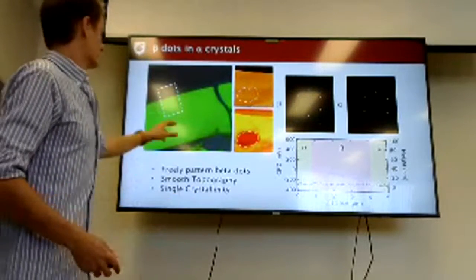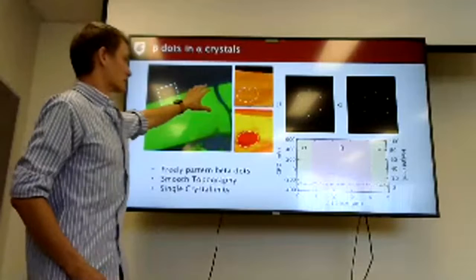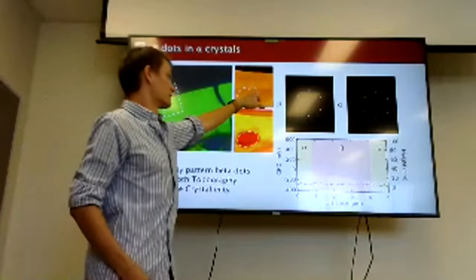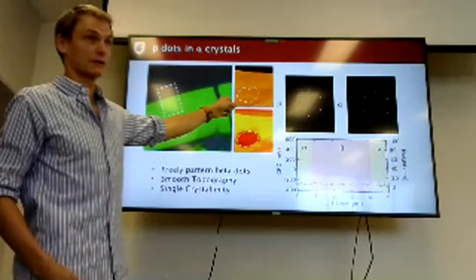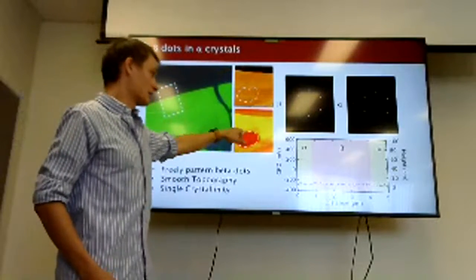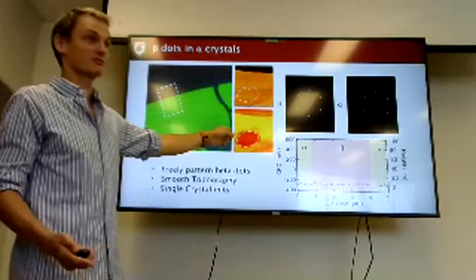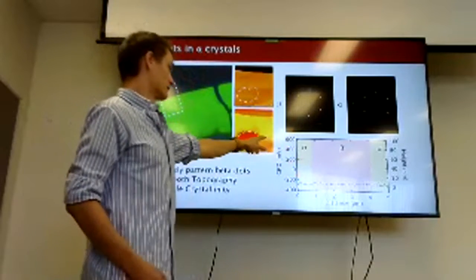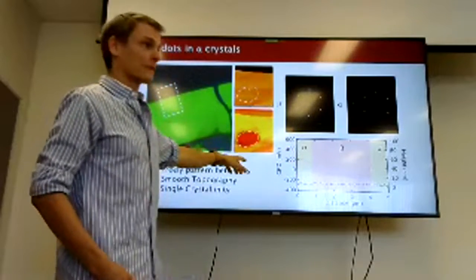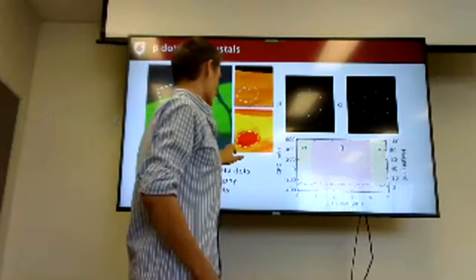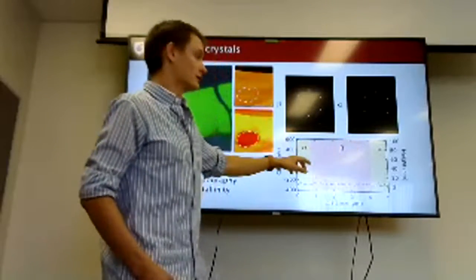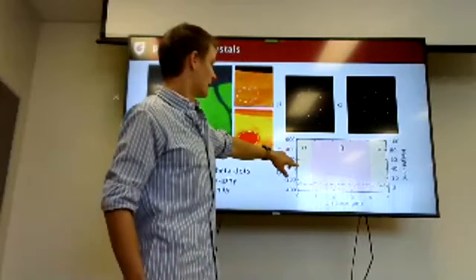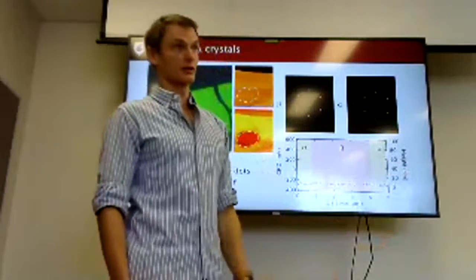So both are true. This little white box is the AFM profile and the KPFM profile, okay? And what we see in the AFM profile is a smooth topography over the interface, which is exactly what we would want. And then what we see in the KPFM profile is not a smooth work function, okay? And then we have the traces here, and these traces are taken across the fat part of this oval, where we have alpha phase over here, beta phase in the middle, and alpha phase. So on the one side, we see the work function difference of about 300 millivolts, 250, and then the topography is smooth, and that is good, okay?